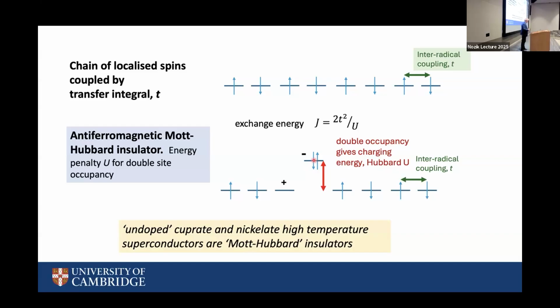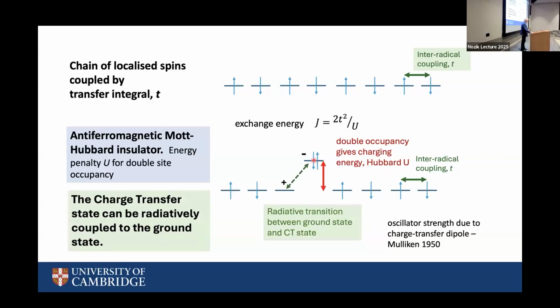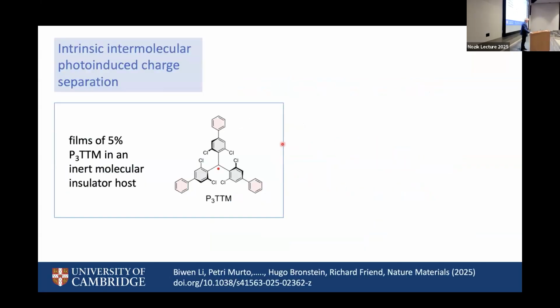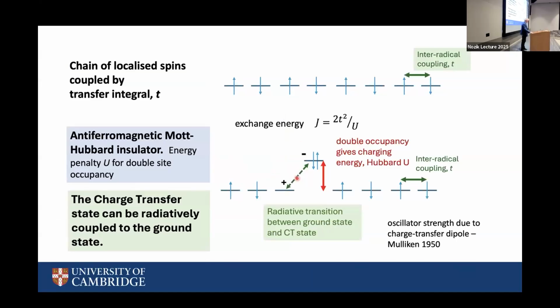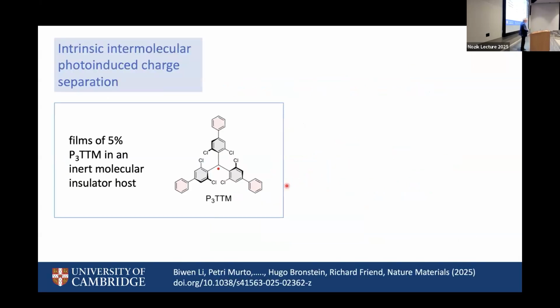And it's quite consequential. What we have realized is that this process of moving charge from one site to the other, so we go from spin up, spin down to nothing at all, and spin up, spin down on one site, is optically active. It's dipole coupled, so it's actually bright. And so going back to the principle that we always want things to emit light, that has been a surprise. So if we could do that, my description of the excitation being one that naturally separates charges, could we make such a material be an intrinsic photoconductor without needing the heterojunction? It's something we find ourselves exploring.